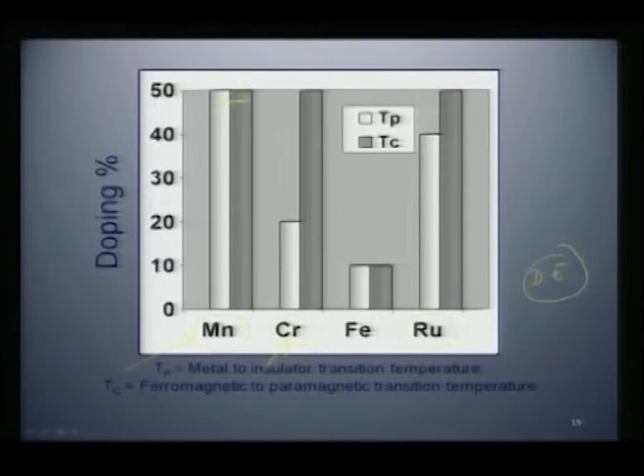If you substitute ruthenium, the metal insulator transition is taken up to 40%, and you also see a strong ferromagnetism up to 50% of ruthenium. Therefore, something very interesting happens in the case of ruthenium substitution, but by and large, when you try to disturb the Zener pair, then the metal insulator transition is decoupled from the ferromagnetic to paramagnetic transition, that is Tc.